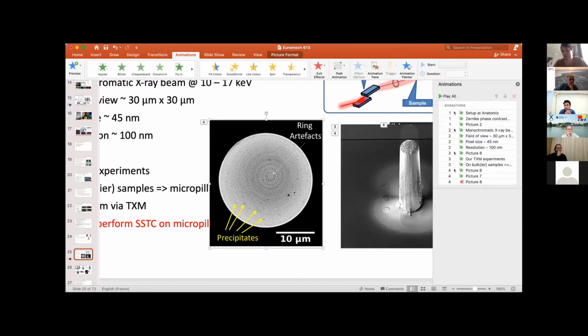So it's basically quite complementary to the TEM work then, in the size range. Except that it's a bulkier sample. Yeah. Right. And this is a limitation also of the technique. If you go to BM32 at ESRF, you get a much higher resolution. If you go to APS, or Diamond, it's much, much higher. So this is just to see if our technique works or not. You mean in terms of pixel size? You can go much lower? Resolution. They go down to 50 nanometers resolution. Pixel size is 22 there.